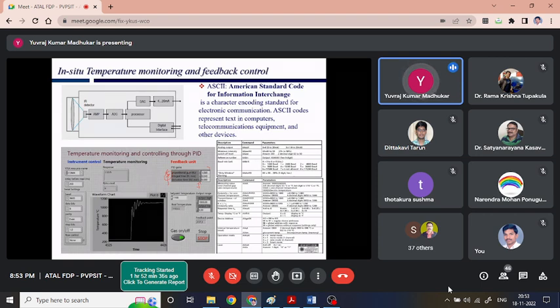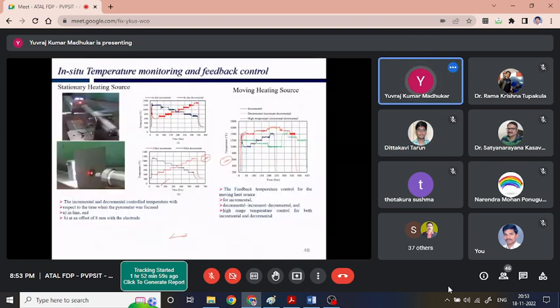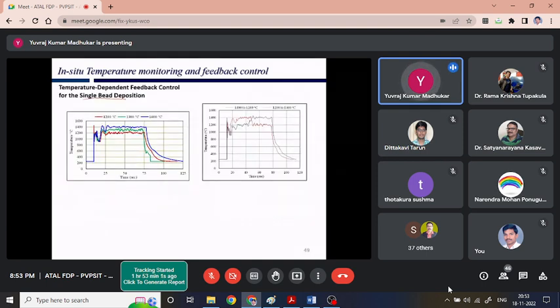Otherwise, in an actual environment, when we start depositing, the process is going to be very dynamic. Plus, we are measuring it at a certain distance behind, so again a lot of the effect of the dynamic nature of the melt pool comes into the picture. We saw in that thermal video that the temperature is very dynamic. So we have to ensure our system works in all kinds of environments. Once we ensure that part, we can deposit single bead, multi-bead, no problem.